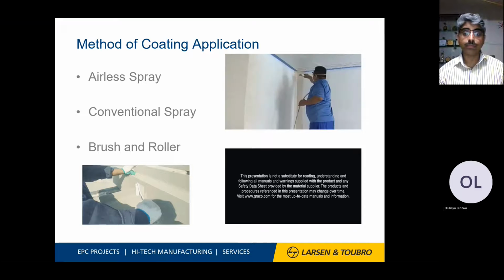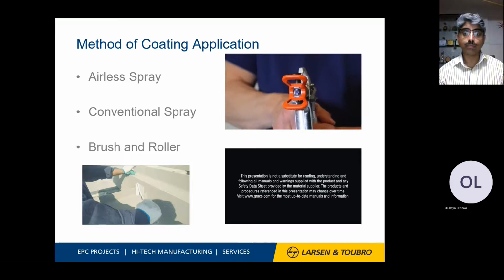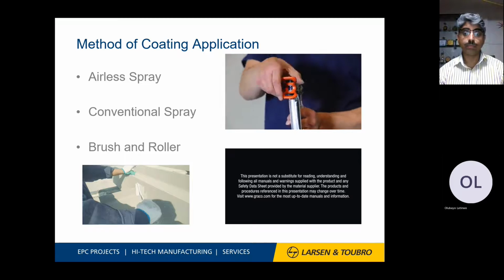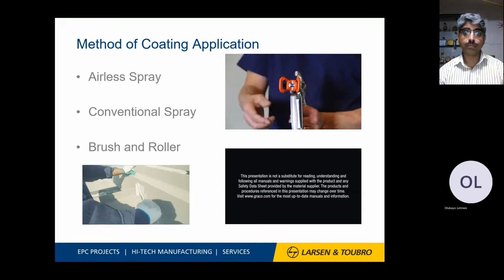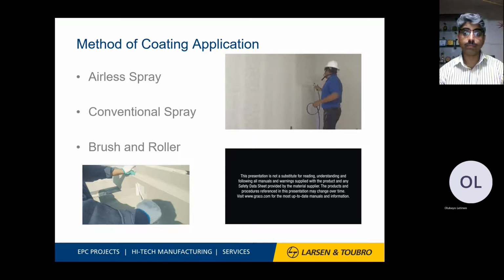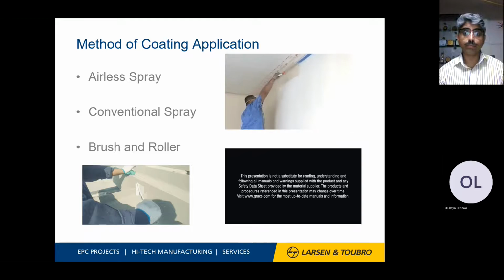Your arm should be moving when the trigger is pulled and released. This will create a nice fuzzy edge around the entire spray pattern so your next pass will blend into the previous pass. Rotating the guard changes the pattern to either vertical or horizontal orientations. When spraying on broad open surfaces, such as ceilings and bare walls, the outside edges should be sprayed first, then the middle can be sprayed more quickly.